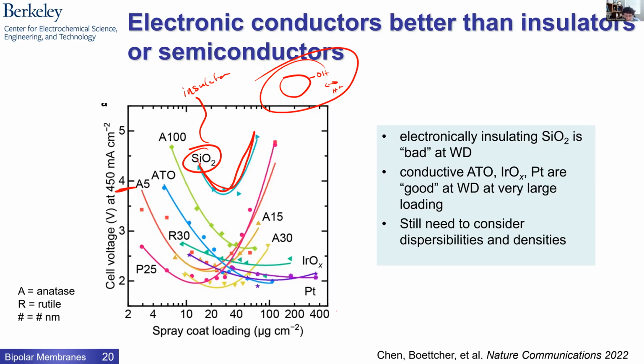And then we went over and measured things that are metallic. Iridium oxide is very expensive, but it's a metallic oxide, so it's a very good conductor of electrons. We noticed for iridium oxide we could go to very high mass loadings and still get fairly good cell performance. Also, platinum dissociates water. Of course, we don't want to use those precious metals practically, but the shapes of these curves are very different. And it's only for these semiconductors, and these different things are rutile and anatase and different sizes. I won't get too much into the details there because there are a lot of convoluting factors, but generally you always see this U-shaped curve when you have semiconductor particles, with a narrow optimum. So this is really interesting.